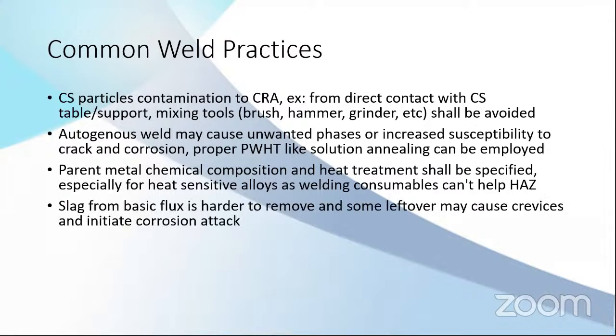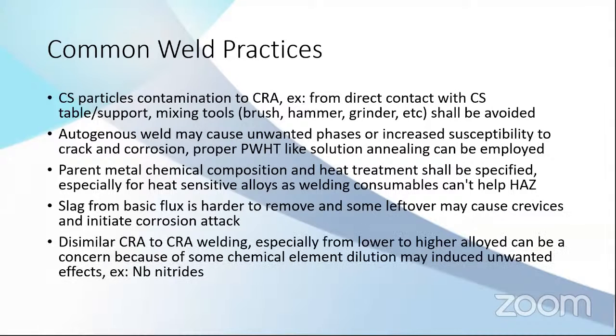And this is just a precaution when you are inspecting the welding. If you are using basic flux, it's harder to remove, so it can cause crevices, and it can be an initiation area for corrosion attack. Dissimilar welding, if it's corrosion resistant to corrosion resistant and very different in grades, for example stainless steel to alloy 625, you need to have concern, because some chemical element dilution can cause unwanted effects, for example creation of nitrides and other phases. It needs to be seen on a case-by-case basis.